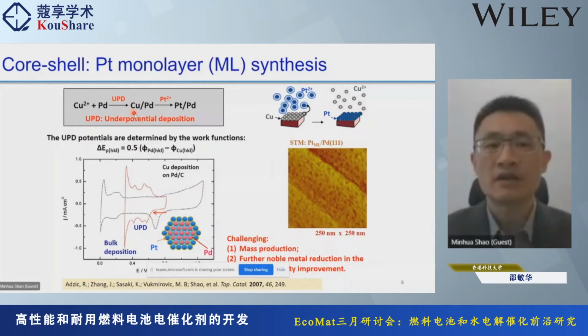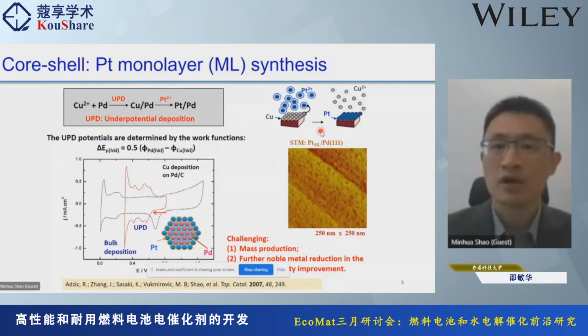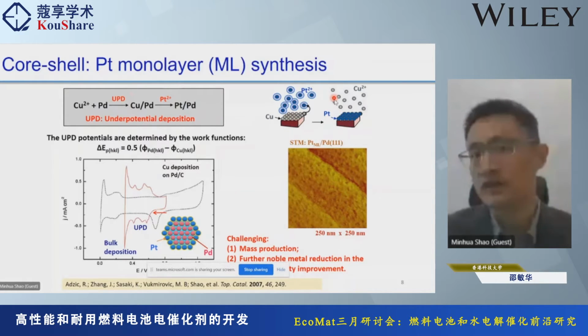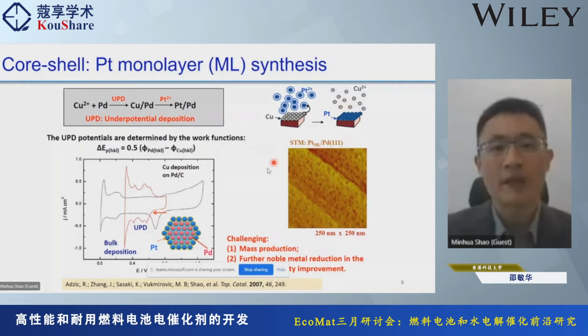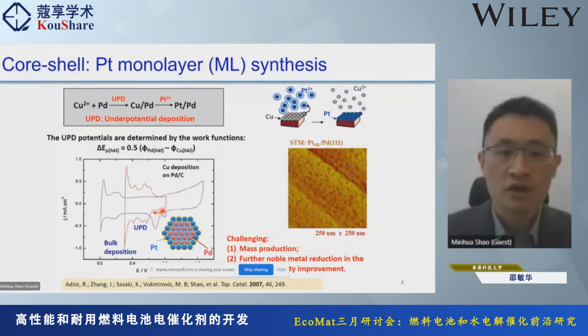And then with this monolayer, we can replace the copper by putting this system in a platinum solution. So this will be a one-to-one ratio exchange. Ideally, one monolayer of copper will be replaced by one monolayer of platinum, right? So you can see that we tried this system with palladium nanoparticles.